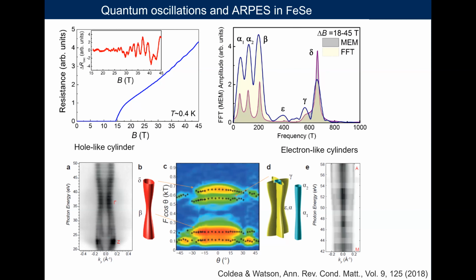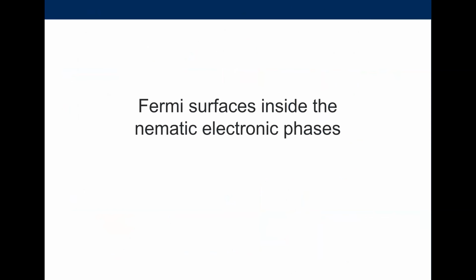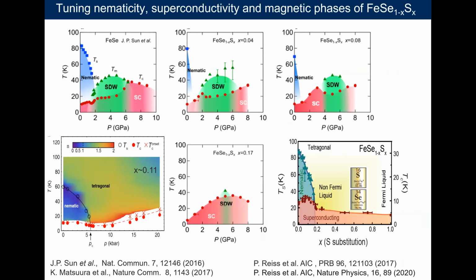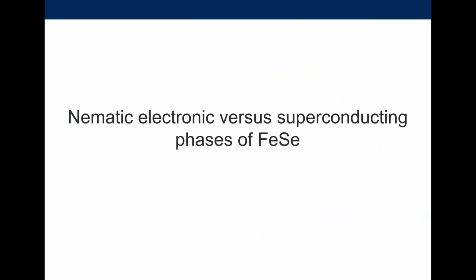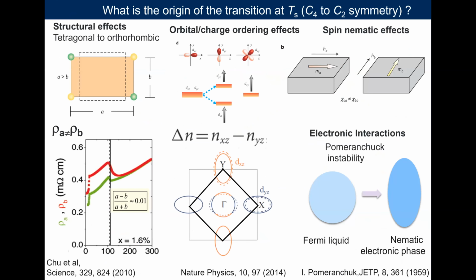The bond singlets can make S dot S dependent on direction, breaking, for example, tetragonal symmetry. So if it was more singlet in the X direction than the Y or something like that, then this would be spin nematic. Yeah. So your susceptibility along the A and B direction becomes very anisotropic, or the spectrum of excitation, of course.